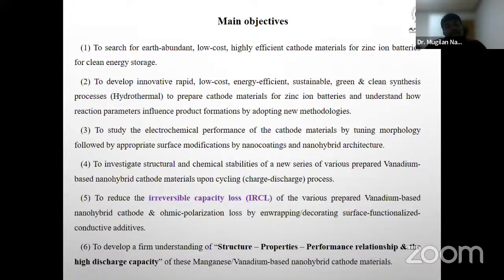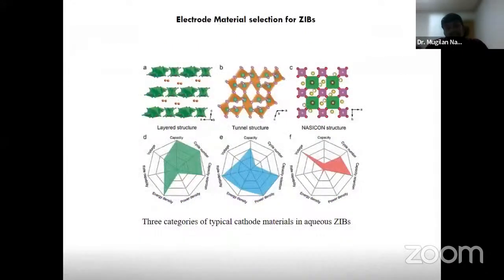And the real motto of this project is to reduce the irreversible capacity loss, which was more in the lithium-ion battery when compared to the non-aqueous medium. We will be focusing here more on irreversible capacity loss of the nanohybrid cathode material. Finally, we develop a firm understanding of the structure, property, performance relationship of high discharge capacity of either manganese or vanadium-based nanohybrid cathode materials.